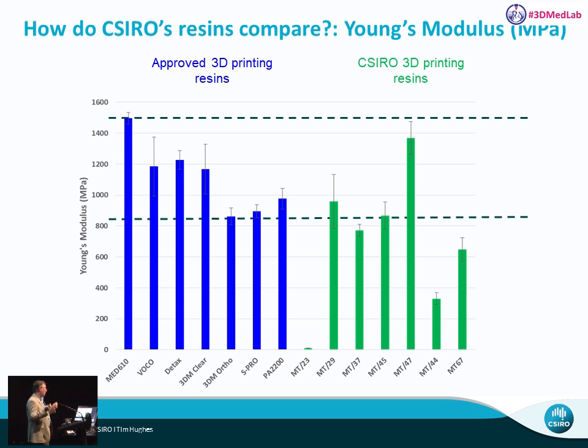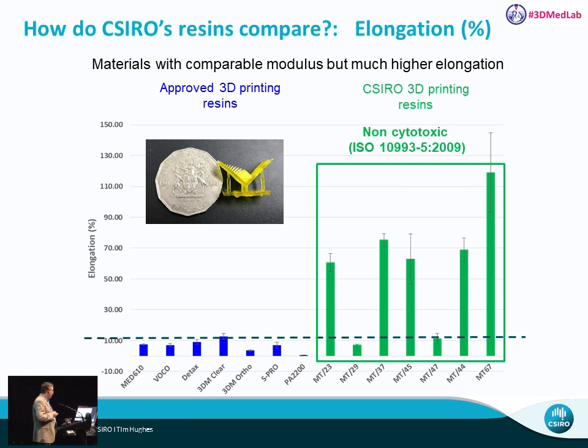But if we look at elongation, which is a measure of how much the polymer can be stretched, you see quite a big difference. Here, the commercially available materials, as I said earlier, are very stiff and brittle, and they don't stretch very far. They're only about 10% and they break. Whereas we can make materials that have comparable Young's modulus, but much higher elongation, up to around 120%. So they behave more like thermoplastics than thermosets. Moreover, we've tested the cytotoxicity of many of these, and they're non-cytotoxic. And we can also print parts with very small features in really high fidelity.